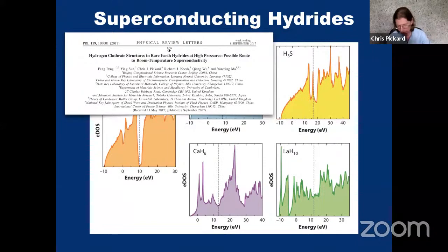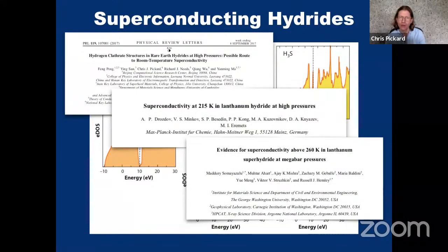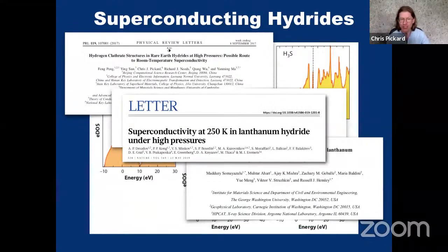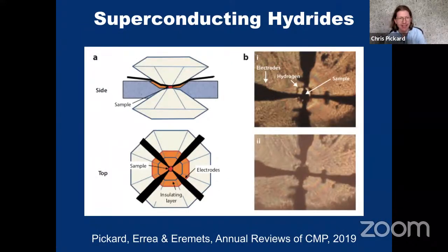But the paper was published, and to our great surprise, very rapidly, within a year, these experimental papers appeared on arXiv. So Mikhail Eremets found lanthanum hydride superconducting at 215 Kelvin. The Carnegie group in the US, Russ Hemley and co-workers, at 260 Kelvin. It's getting quite exciting. And then by the time that Mikhail Eremets' paper was published in Nature, it had gone up to 250 Kelvin superconductivity in lanthanum hydride. So actually, we were on the right track with that prediction. Now, at this point, it seems like theory is telling the experimentalists where to go and what experiments to do, and then they're finding it. It turns out it's a little bit more complicated than that, and I'll come back to that in a second.